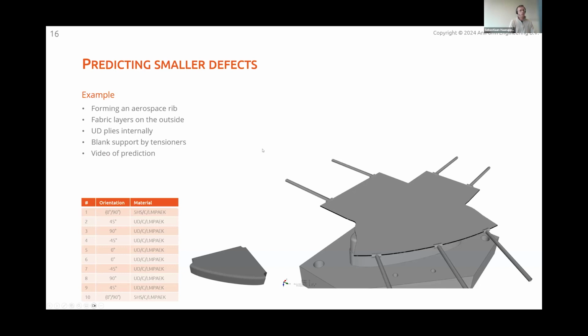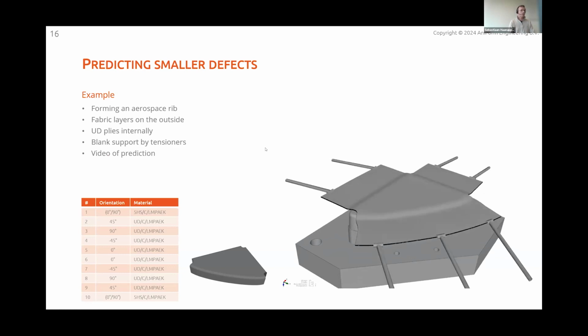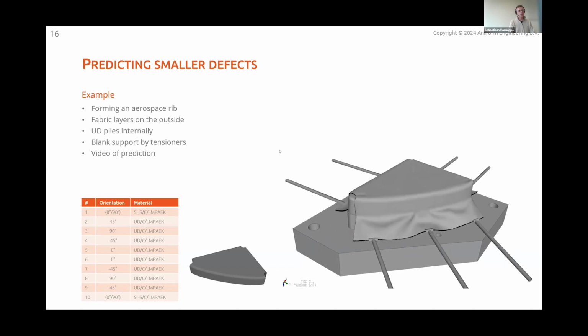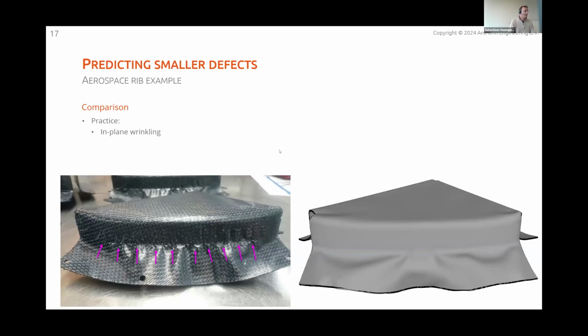And then we can do a prediction. And it looks like this roughly. Well, not so much going on, I think. And when we compare with a real part in practice, then we can see that there was actually quite some in-plane wrinkling going on, especially in this curved flange. But if you look in the simulation, that is not so obvious at the first glance. So it's not so clearly visible, these kind of defects, the smaller defects we see in practice.